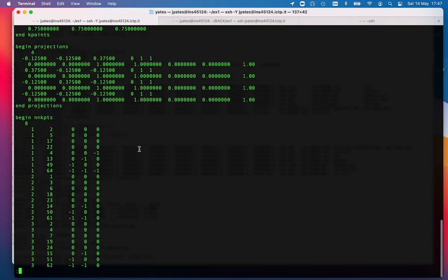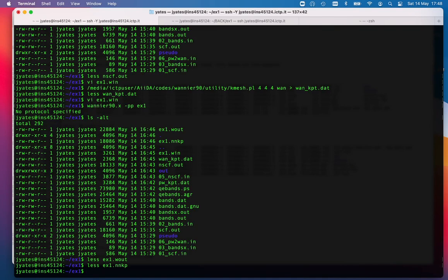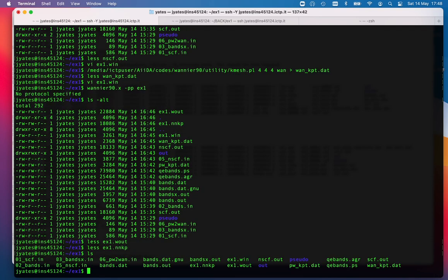And then there's a specification of for each particular K point, we need the overlap with its neighbors. And this is a specification of exactly which K points we need overlaps between. Okay, so that's really for QE to read. So we now need to run pw2wannier90, so all those overlaps can be computed in the plane wave code. And there is a file 06.